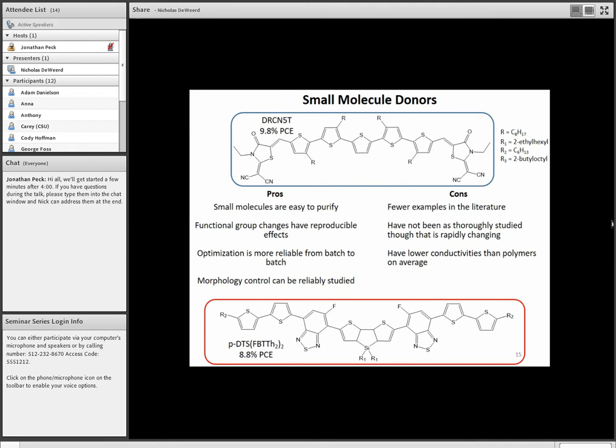And so that has led, on the research side, to a lot of studies on how we can exactly control this complex morphology that we're getting in these bulk heterojunctions. And that's led to some huge strides. You see the efficiencies on these small molecules of 9.8% and 8.8%. All these efficiencies, whether they were polymers or donors in this case, are all optimized against PC70BM, and so that's why I really liked these comparisons.